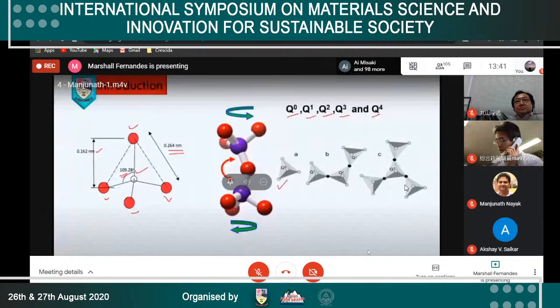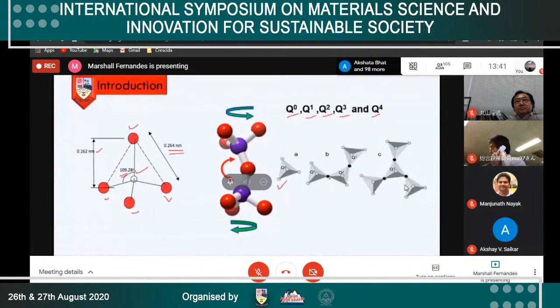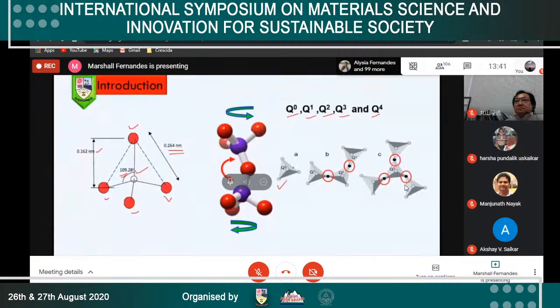A completely isolated silica tetrahedra as shown here is known as Q0, and the one here where the corners are shared by two more tetrahedra is known as Q2. So basically the Q values depend on the number of corners shared by the other tetrahedra. I repeat, only the corners shared by the tetrahedra and not any other individual atoms or ions. So the higher the Q value, the more connectivity, and the lower the Q value, the less connectivity between the tetrahedra. That is, these structures are more of an open type.